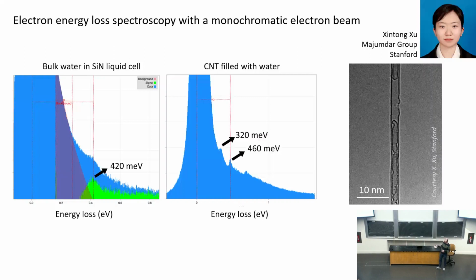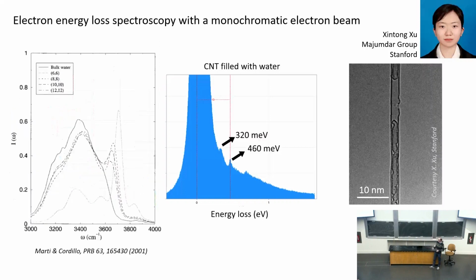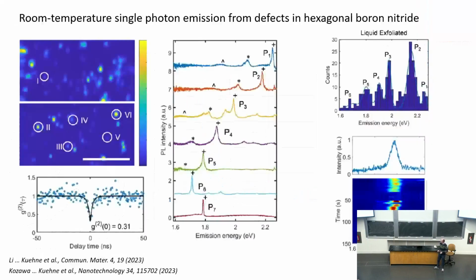This has been recently shown at the APS March meeting, but we are very excited about the opportunity to be able to probe the confined fluid directly without having a mediator, in a sense. And there's a lot that will be done in this space. These are some early MD predictions here for these modes. And that also suggests that when you go into smaller and smaller CNTs, you should start to see a peak like this emerge at a higher frequency, which could reflect the signal we observe.